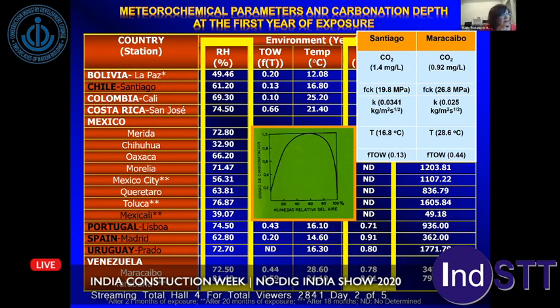It has been reported that the electrolyte layer on a metallic surface decreases at relative humidity over 80% when the average temperature is over 25 degrees C. In other words, time of wetness is lower than the one established by ISO 9223. Therefore, even with a high relative humidity, if temperatures are higher than 25 degrees C, the concrete will be dry enough to easily allow the entry of CO2 in Maracaibo, Venezuela. Not all the test sites follow the behavior observed in the Maracaibo test site.